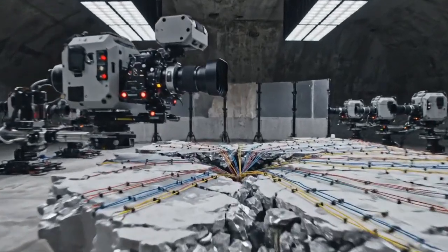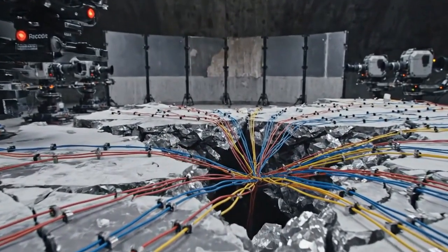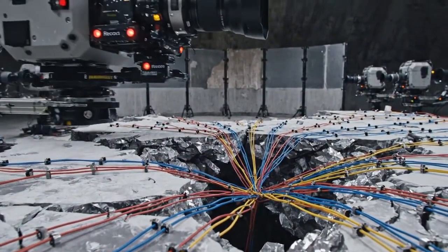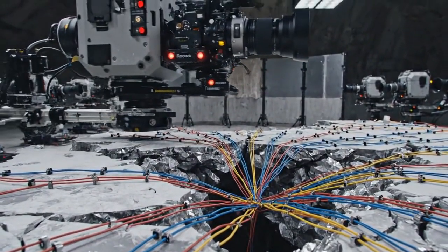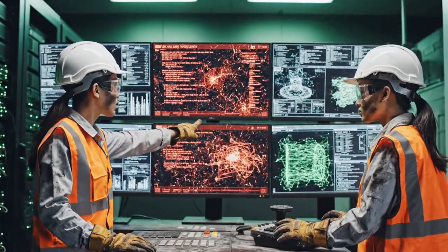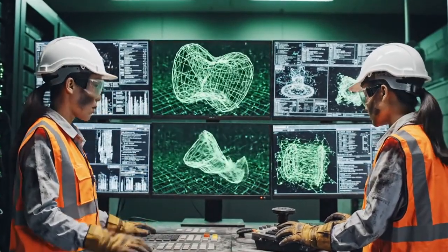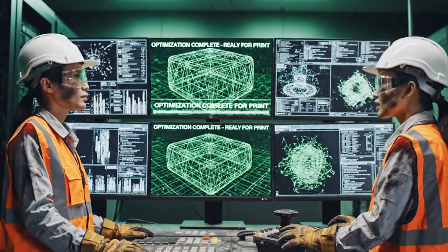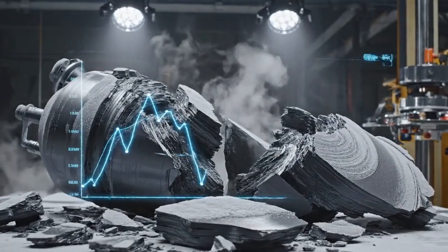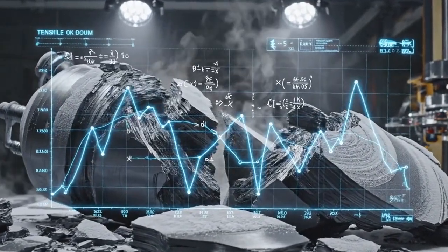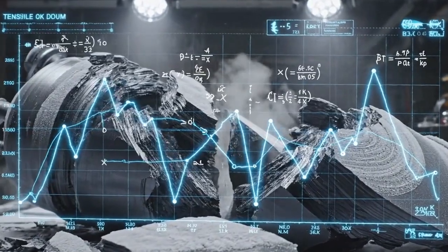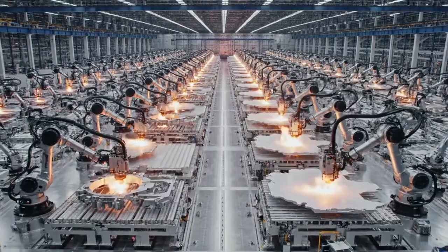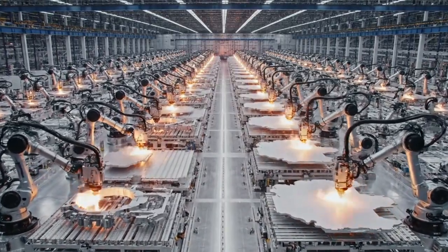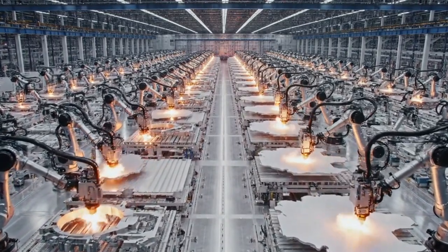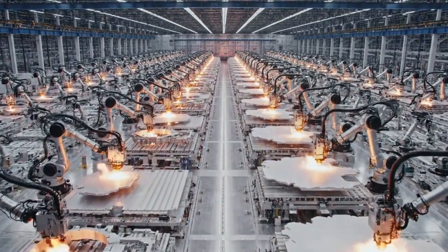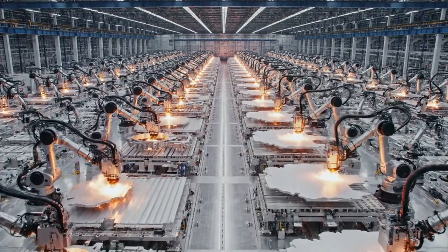High-speed cameras recording at tens of thousands of frames per second and thousands of strain gauges capture the exact millisecond of mechanical failure. This destructive data is paramount. It calibrates the topology optimization algorithms, proving exactly how the 3D printed alloy behaves at its absolute tensile limit under cryogenic conditions. The successful validation of these monolithic structures triggers a fundamental paradigm shift in the macroeconomic landscape of aerospace